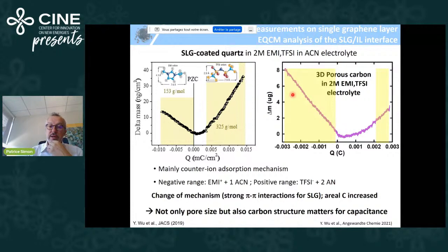Still, very nice charge storage for cations, but here we have this huge ion exchange zone for porous 3D carbon that we don't see anymore clearly on the graphene side. So what it means finally is that not only the pore size is important for capacitance, but also the local carbon structure. And this carbon structure has an impact on the charge storage mechanism.